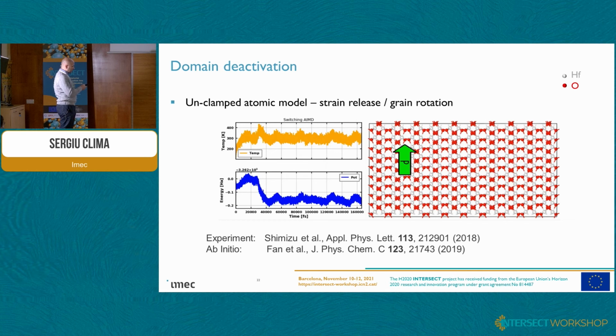But what you can observe in this simulation is that at certain point, the polarization in this ferroelectric material rotates 90 degrees. So here it's perpendicular to the in-plane, let's say X direction. And at certain point in time of the ab initio molecular dynamics, it rotates 90 degrees, becoming parallel to the X direction.